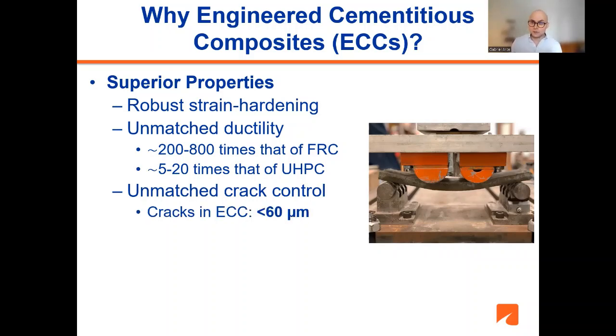Also, it has unmatched crack controllability. Cracks in ECC are steady state controlled to usually less than 60 micron. Why is this very important? Because this allows these cracks to be self-healing. Concrete has autogenous healing properties. However, these autogenous healing capabilities are usually effective only with tiny, tiny cracks. This range of crack size is appropriate for this healing. And also, it has been demonstrated through research that cracks around 50 to 100 micron do not increase the permeability of the cementitious system. So, in short, these cracks in ECC are not a problem for durability. Also, for context, cracks in UHPC, for instance, are usually greater than 100 micron. And in that case, if you have a UHPC with this type of cracking, you can actually increase the permeability of the system.